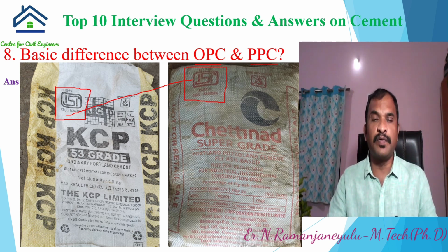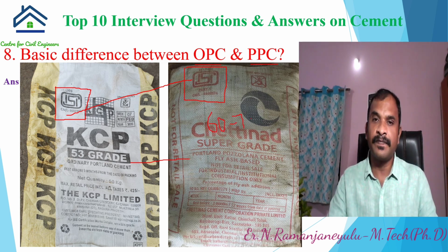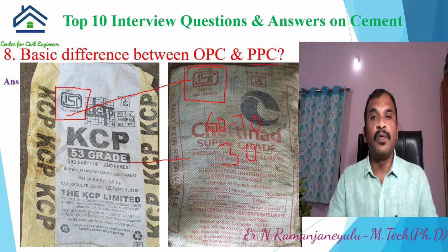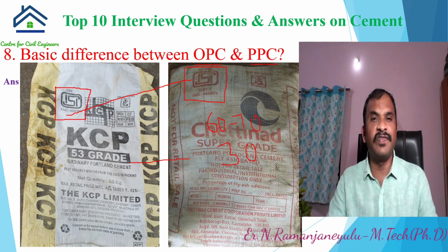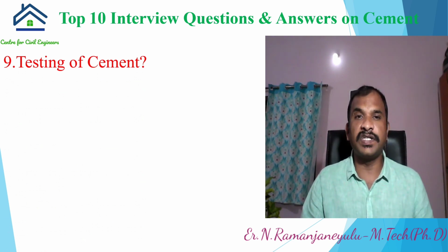Regarding manufacturing process, up to manufacturing of clinker, both processes are same. After getting clinker, OPC clinkers, if you want to prepare PPC cement, we have to take 60 to 70% of OPC clinkers. Then remaining 30% we have to take fly ash or rice husk ash. By taking any of pozzolanic material, we can mix in the clinker and we can grind. Then we are going to get the cement called Portland Pozzolana cement. This is the basic difference between OPC and PPC.